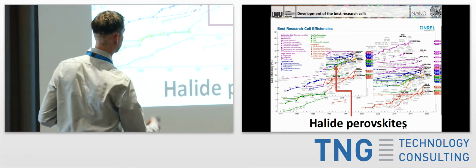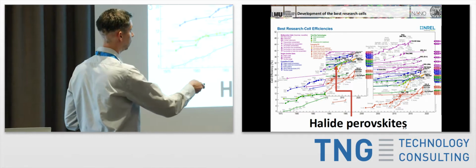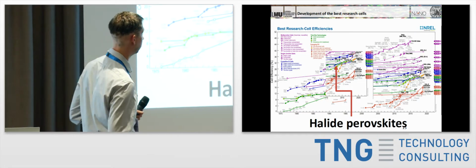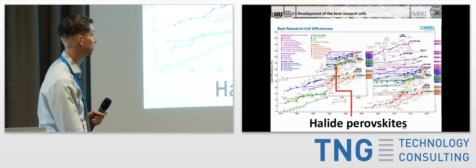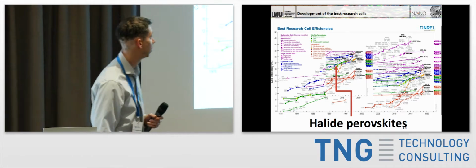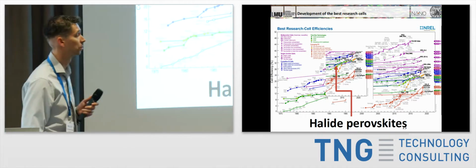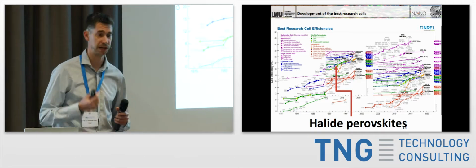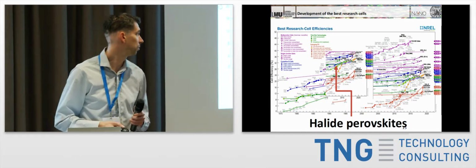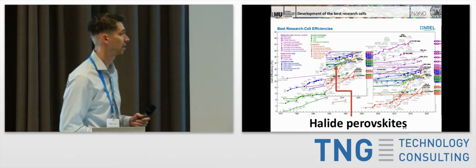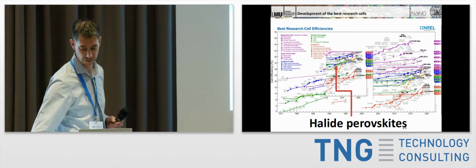So it started out in around about 2011, the first certified solar cell, and you can see that it's been increasing much, much faster than all of these other technologies. It's quickly overtaken some, now is up to a value of about 24.2%. This is only within about 7 years that it's actually been able to do that. So essentially, it's been able to improve as much as silicon has in 40 years in only about a fifth of the time.